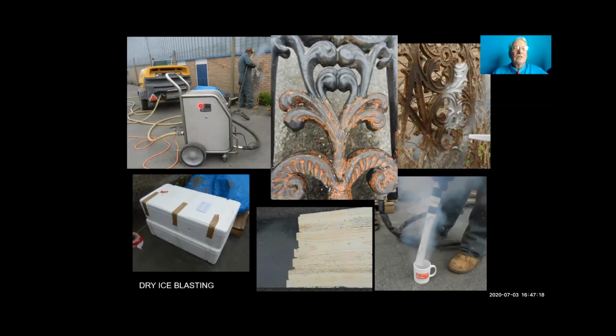The machine, of course, has to be fed with this dry ice that comes through the post or whatever, and you've got to use it within about 2 days. And it's fairly effective, but of course it does make it wet. And if you hold the nozzle in the one place for too long, you end up with ice on your metalwork. It's not totally effective, I have to say, on metal.